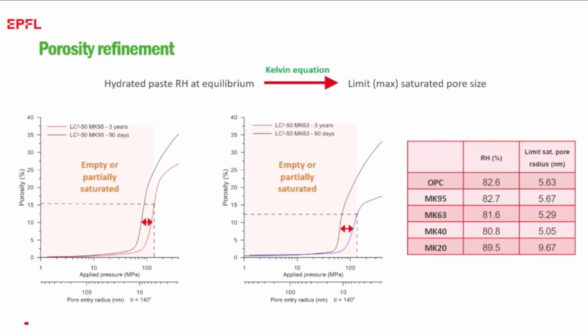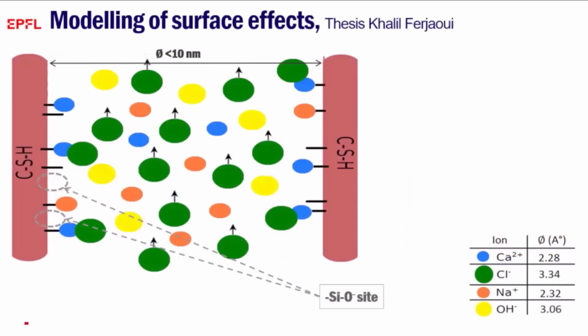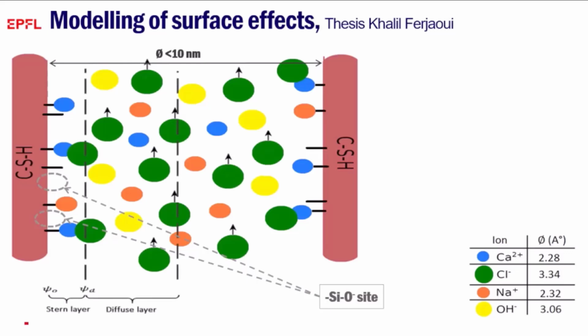What's particularly important is the fact that in practical materials, we've got relative humidities which go down quite significantly. So we're not at 100% relative humidity, and this means most of the pores are empty. You can see here in these long-term experiments that after 3 years, the radius of pores that can still contain water is only 5 nanometers. And in those 5 nanometer pores, you have a very complex interaction of the ions with the CSH surface.